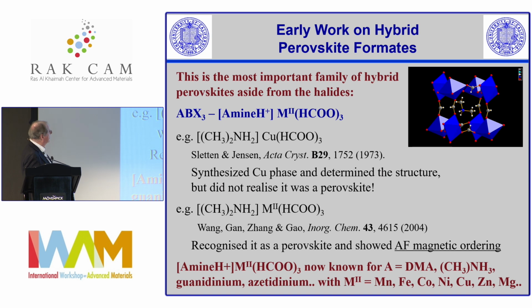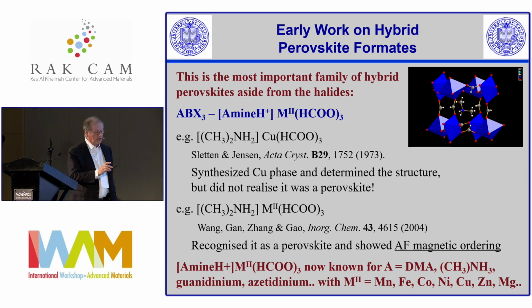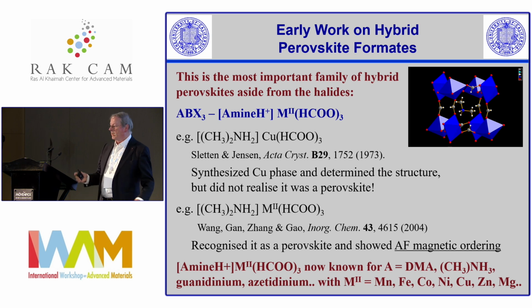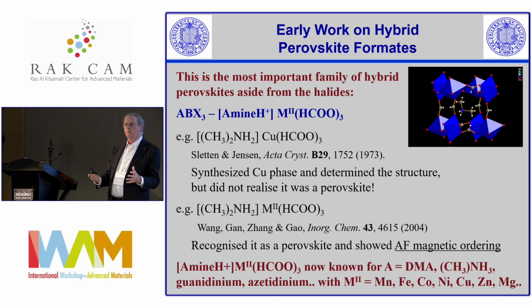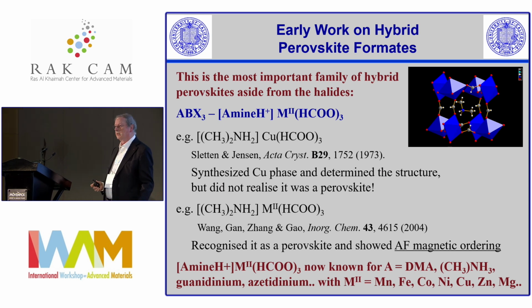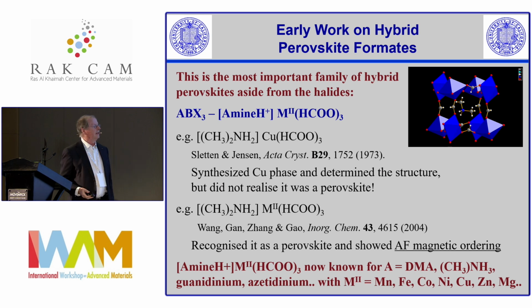So the early work on hybrid perovskite formates is quite interesting. Sletten and Jensen published a paper in '73, so that's about 50 years ago, with the structure of this copper phase, dimethylammonium copper formate. The funny thing was, it had the perovskite structure, but they didn't realize that it was a perovskite, because they were molecular chemists and they just drew the structure as if it was a molecule and didn't connect it together the way that we do with all our structures nowadays. And so they missed the fact that it was a perovskite. If you look back at it and build it in the software, then you can certainly see that.